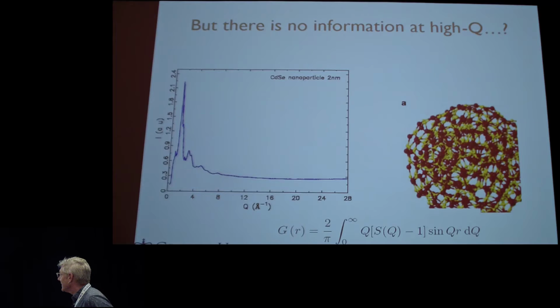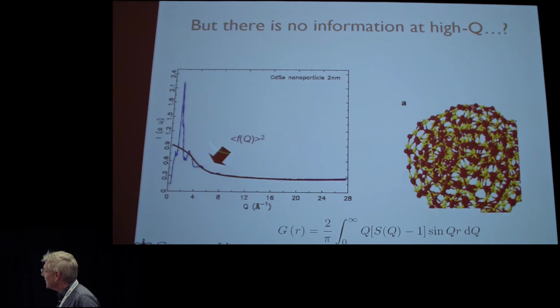And a little bit of magic that gives us that enhancement in the information content comes through the normalization. So this is actually a scattering pattern coming from a quantum dot, a cadmium selenide nanoparticle that has a 2 nanometer diameter. And what you can see is it's broad and it's diffuse, and it only has a few peaks, just like that other one I showed you. And it has a long, long, long flat part out here at high Q, which for years and years and years we were throwing away. But when we do the normalization that we need to do to put it through this Fourier transform, we have to divide the scattering by the scattering cross-section of the sample, which is the atomic form factor squared. And the atomic form factor squared is a smoothly varying function like this.